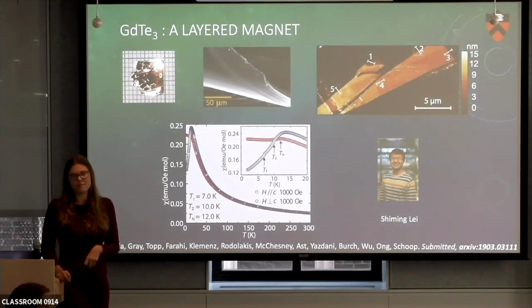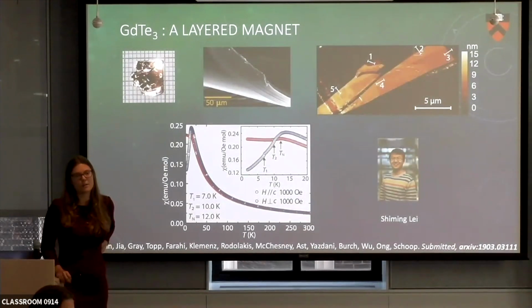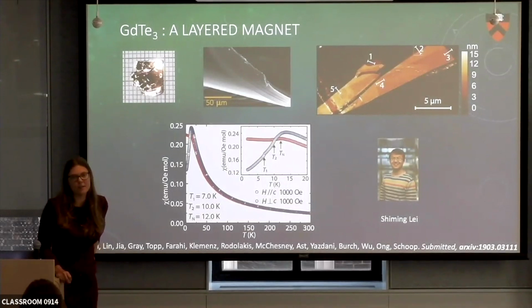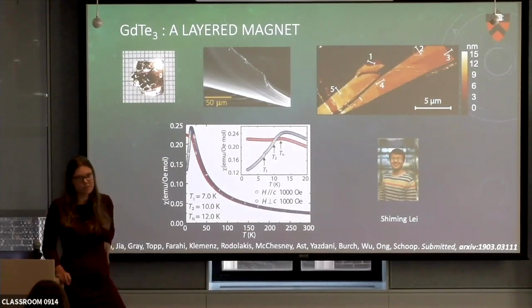Yeah. What I'm saying is that Igor Mazin wrote a very well-known paper. I mean, it's 240 citations, but it basically shows that the electronic mechanism that we think of, nesting of charge density waves, doesn't really happen in quantum materials. I know this paper very well, and I can't completely agree with it, yeah. Three-dimensional charge density waves are very complicated. Yeah, exactly. But I think of them more as structural distortions, similar to Peierls distortion in more dimensions.